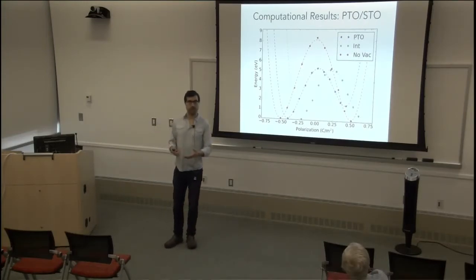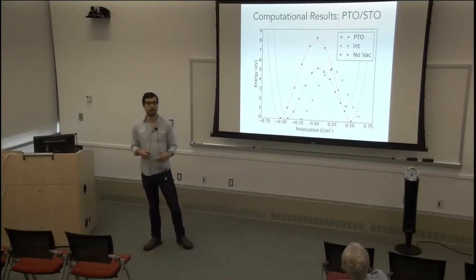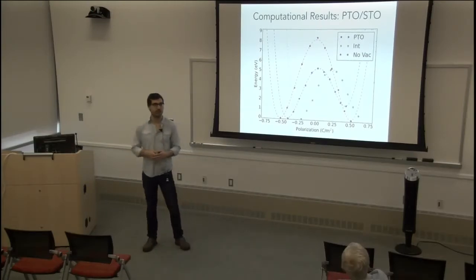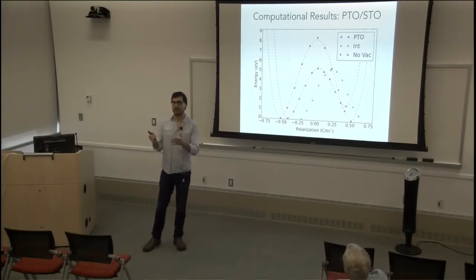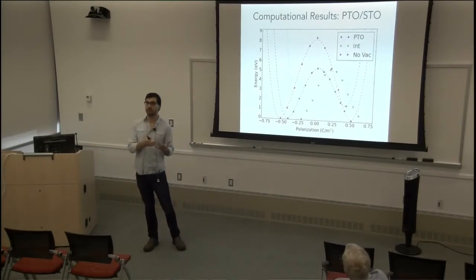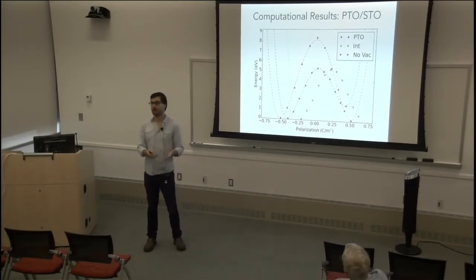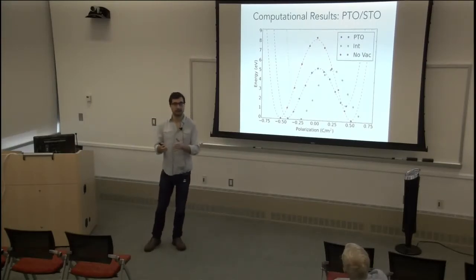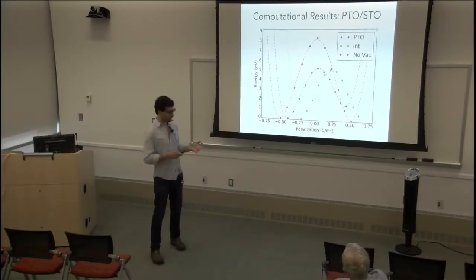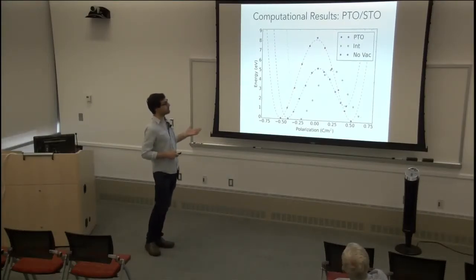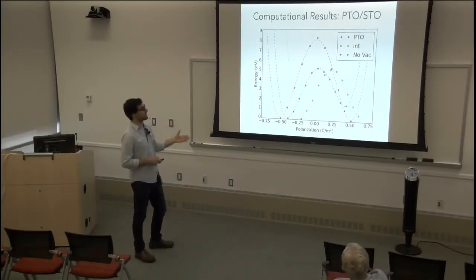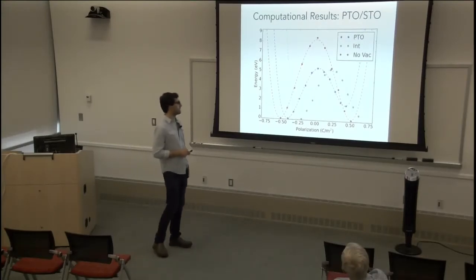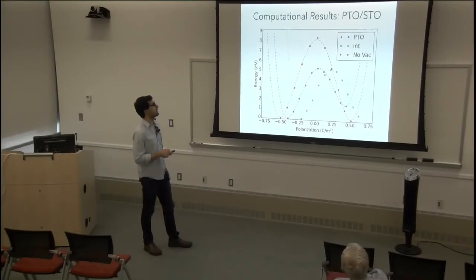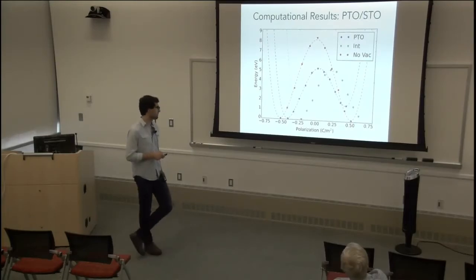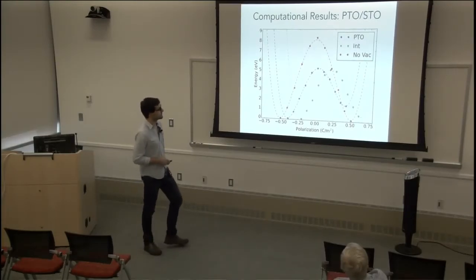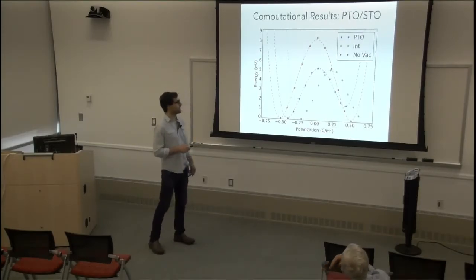And that's because experimentally, when you calculate hysteresis, let's say they calculate a value of 20 in whatever units. And they say, okay, that means that the positive state has a value of 10 and the negative state has a value of negative 10. When in reality, it might have been 15 and negative 5, which still gives you 20. But this is something experimentalists cannot probe, so this has no effect on something measurable. And while you see this, it turns out to be not of importance. And initially we weren't sure exactly what the significance of this shift was.